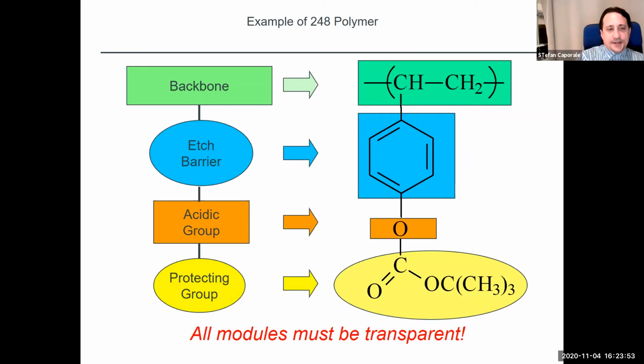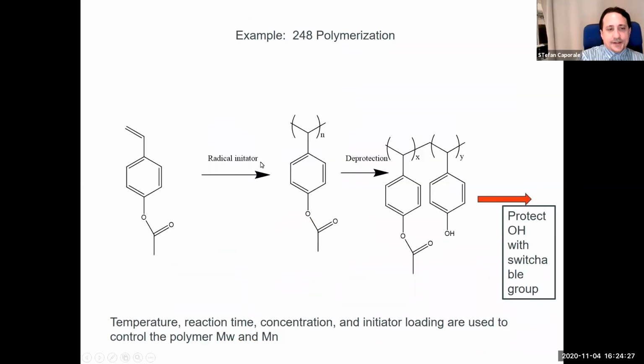So an example of that for 248 was we used the styrenic backbone. These vinyl styrenes react very well through here, and I'll show that in the next slide. The styrenic conjugated ring very much resists the etch process, and the pKa of the hydroxy sticking off here is about 9, making it soluble, very acidic in our aqueous base developer. And then we can use these T-BOC protecting groups, which are very sensitive to acid, and will leave at our desired temperatures. The other nice thing about these styrenic groups is their polymerizations are well studied, which makes it fairly easy for us to do.